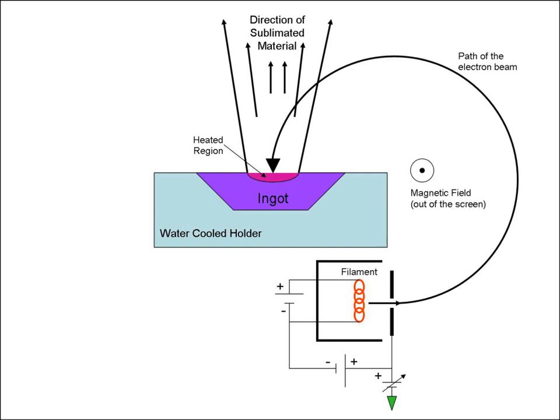The shaft also rotates the substrate at a particular speed so that the film is uniformly deposited on the substrate. A negative bias DC voltage of 200 to 400 volts can be applied to the substrate. Often, focused high-energy electrons from one of the electron guns or infrared light from heater lamps is used to preheat the substrate.